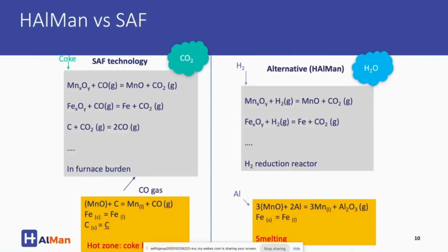Compared to SAF technology, you see on the left in SAF technology we have CO2 emission, but for the HAlMan technology on the right you see we use hydrogen, we use aluminium, and the gaseous product is mostly water vapor, so it's a clean process. And if you look at the reaction on the right, you see we have aluminium oxide form. It's not gas, it's liquid in a slag, and then we can extract this alumina again from the slag. Next slide, please.